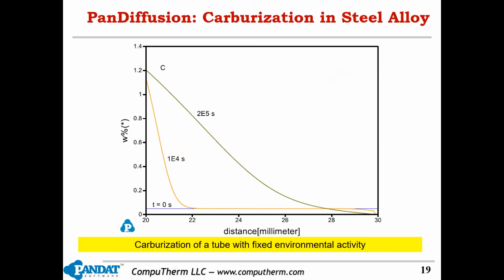And one good application with the Pan diffusion module is the carburization simulation. So in this figure, we can simulate how carbon from the environment diffuses into the steel matrix. So this is an early stage, and this is a later stage. So it clearly demonstrates how carbon can diffuse into the substrate. Of course, you can define different boundary conditions, such as you can fix the carbon activity, or you can fix the flux of carbon, right?